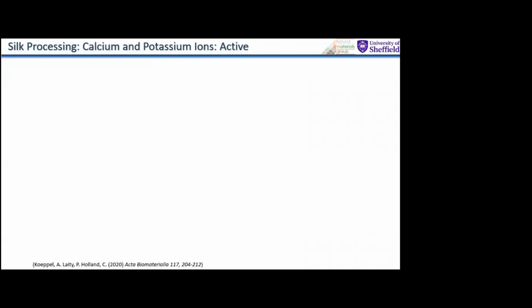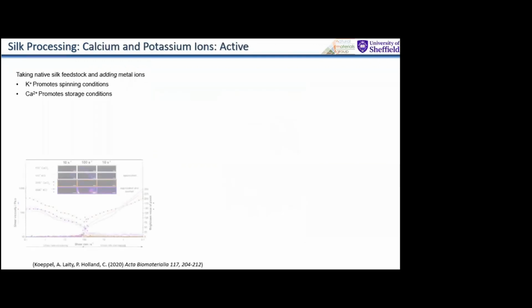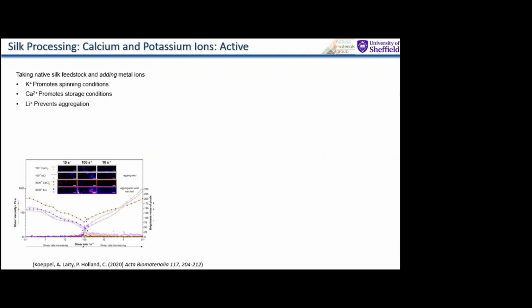That's a chemical way of changing the flow properties. But we tested that, we saw it passively in terms of that's what we observed. We then started adding metal ions in to see if it changed the flow properties of the silk. And what we found is that we add potassium and it makes it more flowable. It also promotes spinning conditions. It makes it easier to transform from a liquid into a solid. It allows for alignment of the fibers.